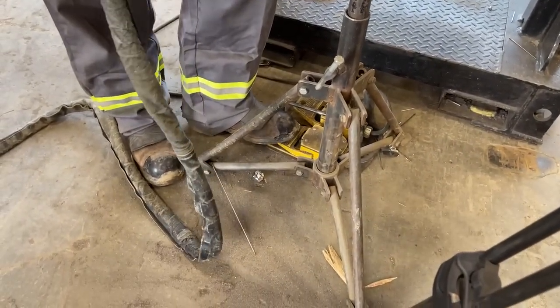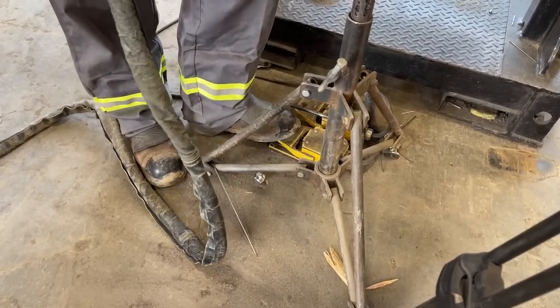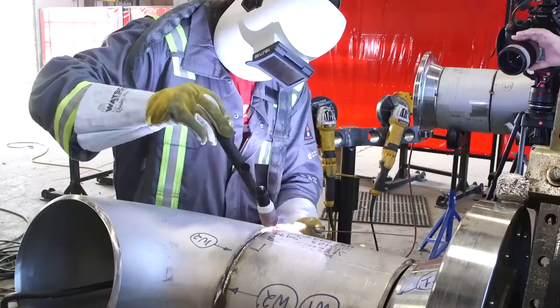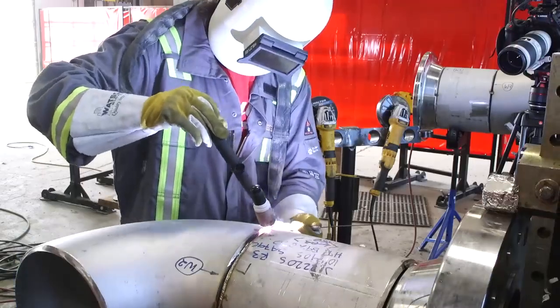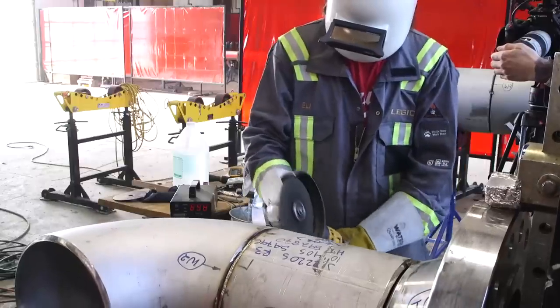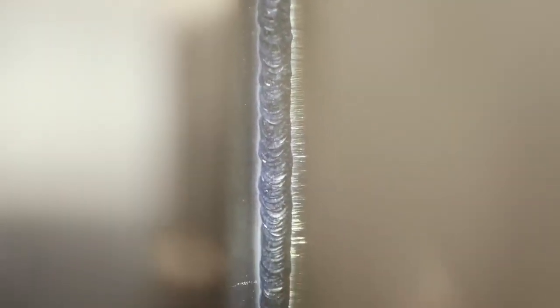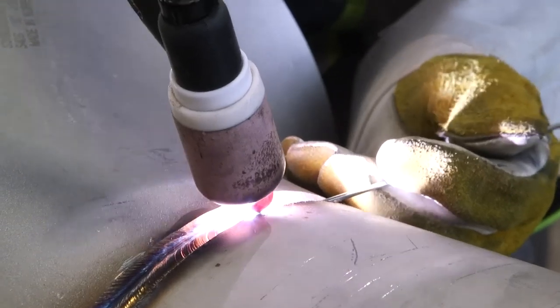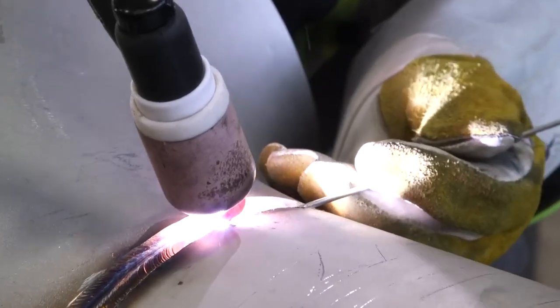There's no heat tint. There's not enough oxygen in the pipe itself to interact with the weld puddle as it elevates in temperature to form oxides to protect the metal. So you'll have no heat tint. If this reads say 30 to 60 parts per million, you'll start getting light straw color. You'll get some yellows. It'll start going up to 60, 80, you'll get some brown colors. You'll get some golds. You go past 100 parts per million, you have blues and purples and beyond.